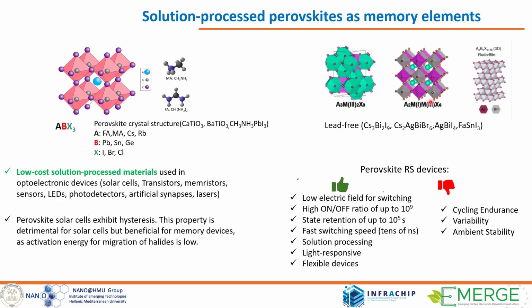So to sum up, perovskite resistive memories, what are the advantages? They have low electric field for the switching, quite good ratio between on and off, so high and low resistance. State retention up to 10,000 or more. Quite good switching, although when we have organic species in the stoichiometry, it's slower than inorganic stoichiometries. They can be solution processed, so low temperature, low manufacturing cost, can be fabricated on flexible substrates. Of course, we can tune the resistance by light, since the perovskites are photoactive.